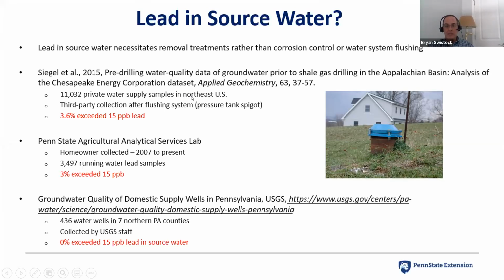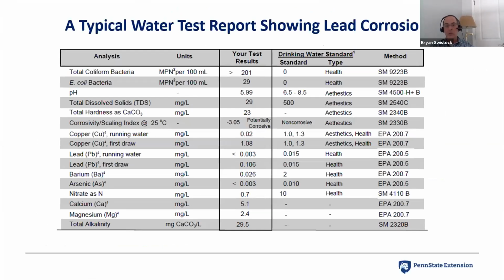So the vast majority comes from corrosion control, and this is what a typical water test report might look like. And I get these almost daily from our laboratory here, where you notice on here we have a pH of 5.99, so slightly acidic water. It's very soft water. It only has 23 milligrams per liter of total hardness. It's got a corrosion index, in this case, the Langelier saturation index of negative 3.05, which indicates a strongly corrosive water. You see that the running water copper was practically nothing, but the first draw copper was over 1 milligram per liter.